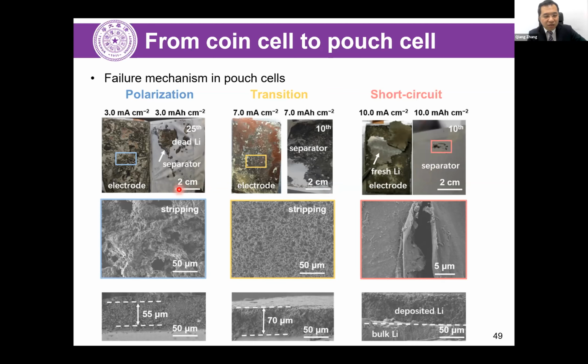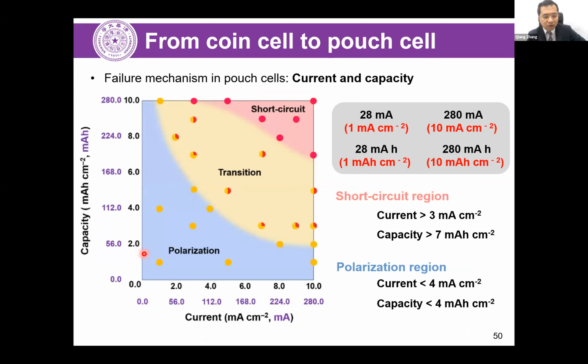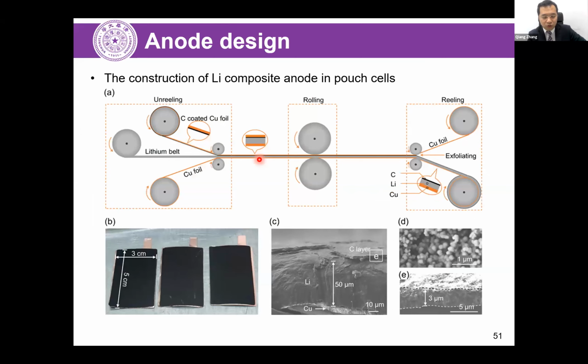And in the mild condition, in which the lithium metal anode becomes powder, dead lithium dominates and the polarization increases significantly. So in this case, how do we overcome the scale-up effects, that is, how do the strategies developed or proposed at the mild condition scale up into the harsh condition? This still requires much chemistry and chemical engineering investigation, which calls for not only the mechanism of transport phenomena and individual reactions, but also engineering materials to realize that.